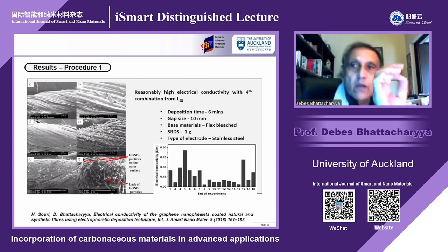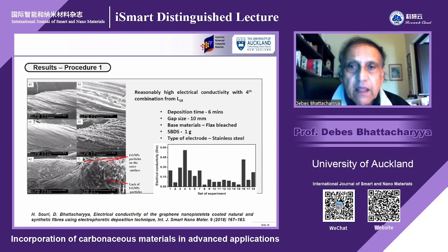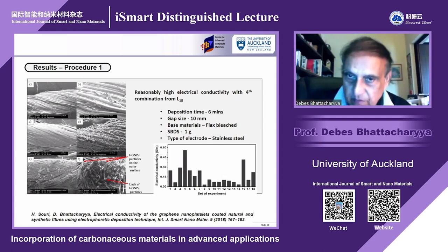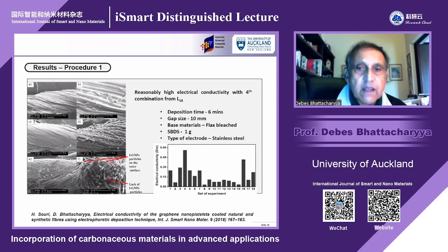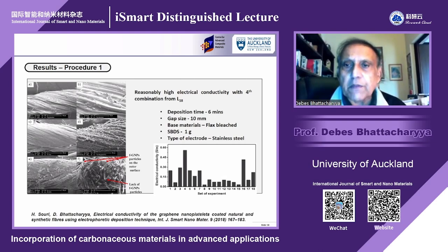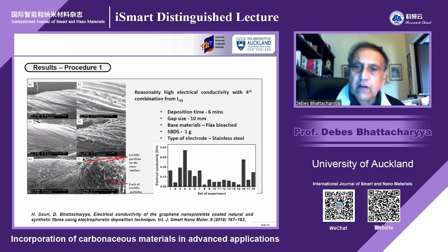By doing that, you can see how the platelets with those carbon black particles can go inside. The deposition time was 6 minutes, gap size was 10 millimeter, base material flax bleached. You can use flax original, not bleached. SDBS was 1 gram, and we used stainless steel electrodes and set up experiments. We also published this one in the International Journal of Smart and Nanomaterials in 2018. That was the first piece of work done with this natural material, and we thought we'd report that. Now, I'll show you a better picture after that.